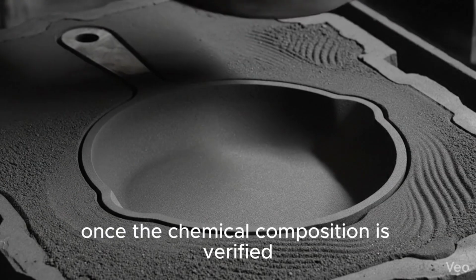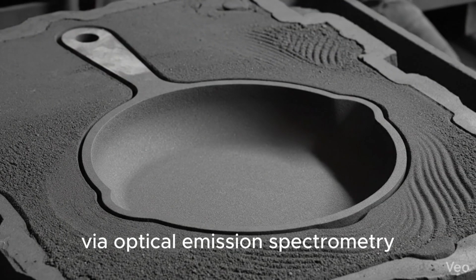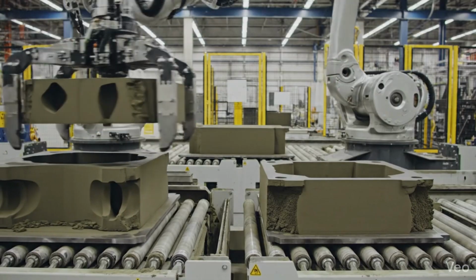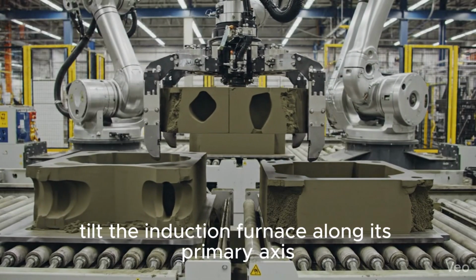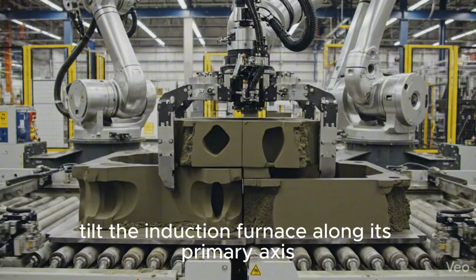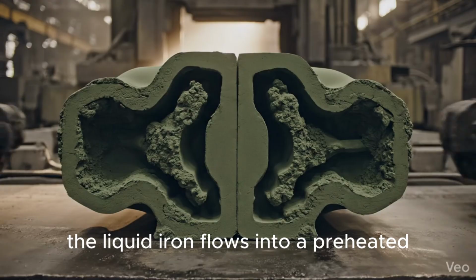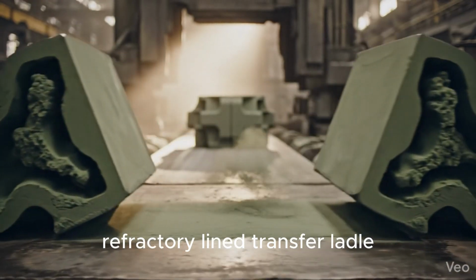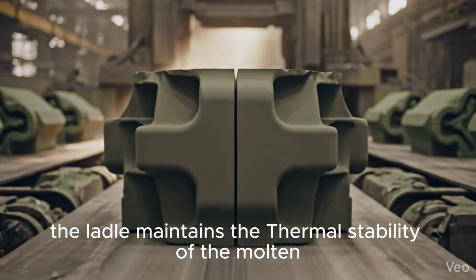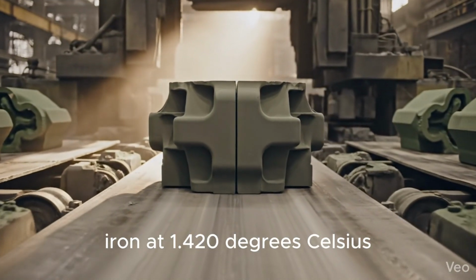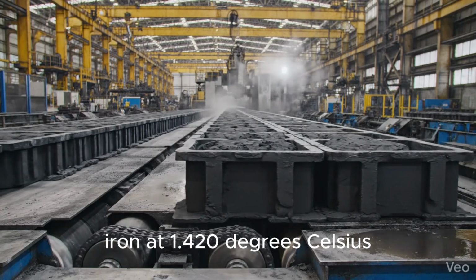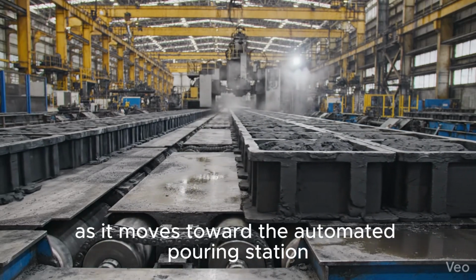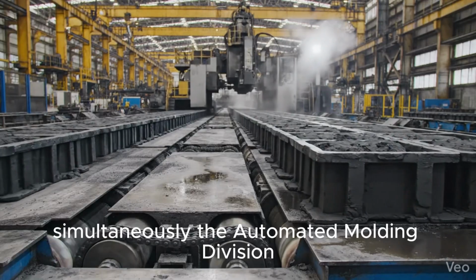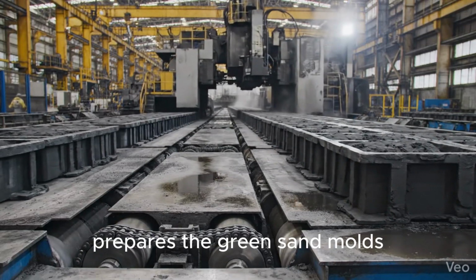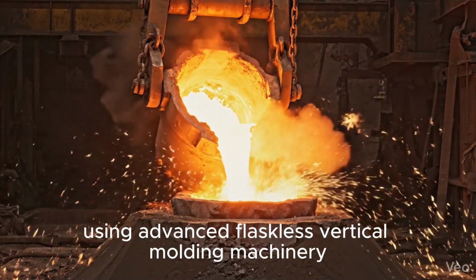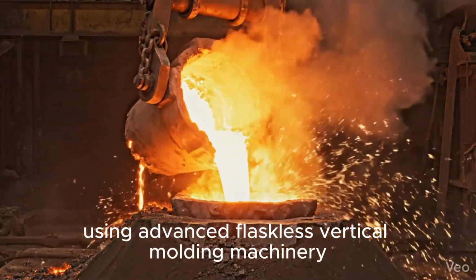Once the chemical composition is verified via optical emission spectrometry, OES, hydraulic cylinders tilt the induction furnace along its primary axis. The liquid iron flows into a preheated, refractory lined transfer ladle. The ladle maintains the thermal stability of the molten iron at 1,420 degrees Celsius as it moves toward the automated pouring station. Simultaneously, the automated molding division prepares the green sand molds using advanced flaskless vertical molding machinery.